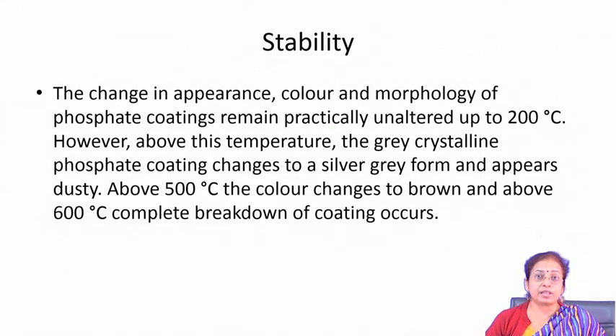So, usually this phosphate coating is not really so stable at high temperature. Up to 200 degree Celsius there is no problem, but above this temperature the grey crystallite phosphate coating changes to its silver grey color and becomes dusty, and above 500 degree Celsius the color changes to brown, and above 600 degree Celsius there is complete breakdown of the coating. So, whenever you talk about phosphated coating, you have to be careful about the application, particularly the service temperature.